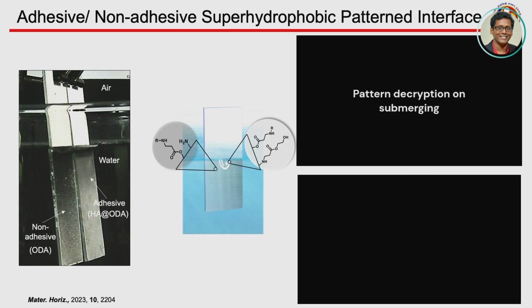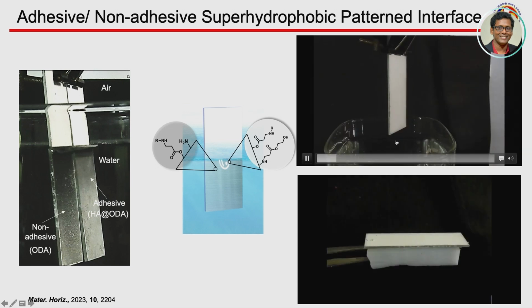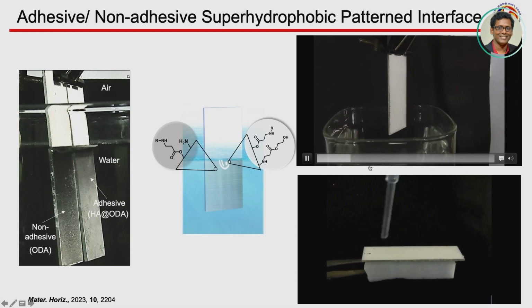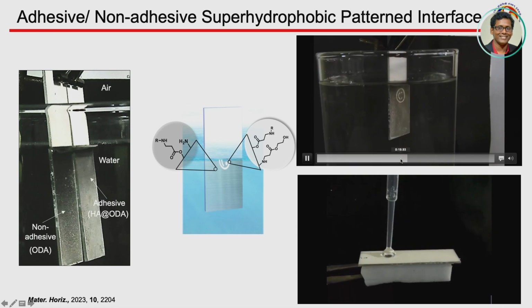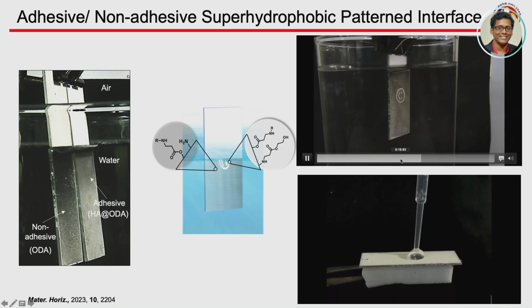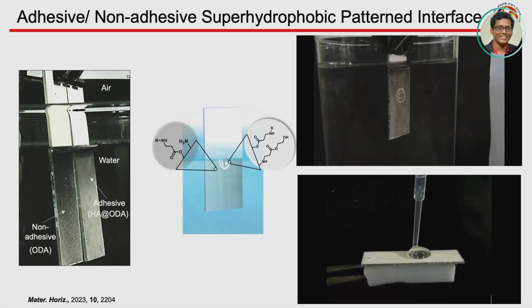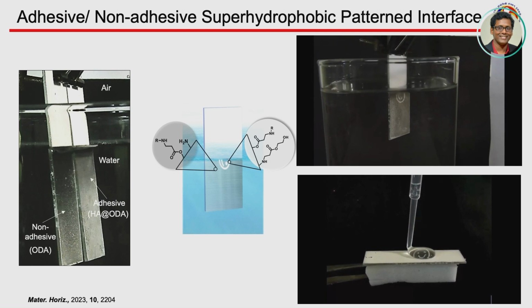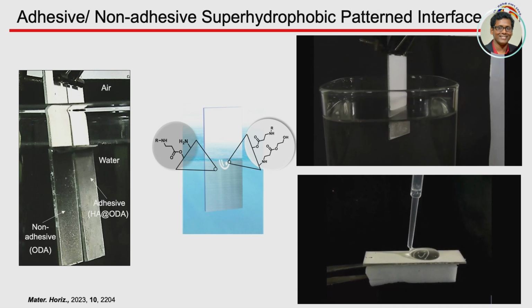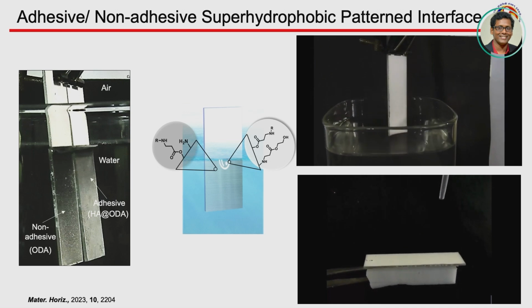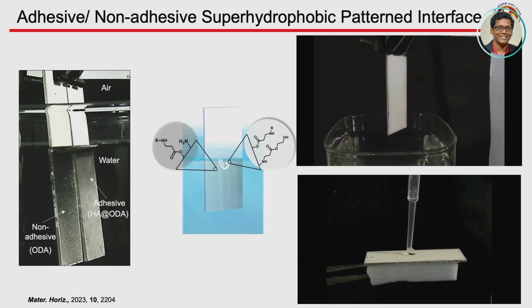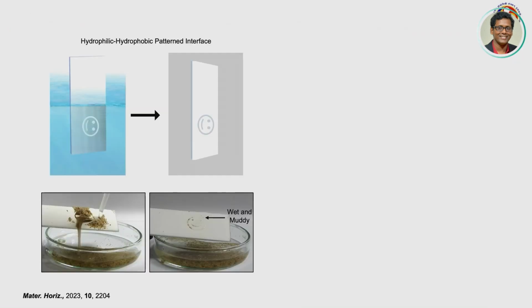And just take a look at this particular video. Initially, you cannot really recognize what kind of information is provided. But once you submerge it under water, not only the shiny portion but also the portion with the dual modification appears, the smiley face. Look here, you put a water droplet that also acts as a lens to visualize a tiny pattern which you left behind on the surface, and when the water droplet is removed, your information vanishes. So that can be a smart way of hiding information on the interface, and that can be useful for anti-counterfeiting applications. And what we did, we have associated these patterned interfaces with fluorescence property to develop multi-level anti-counterfeiting interfaces.